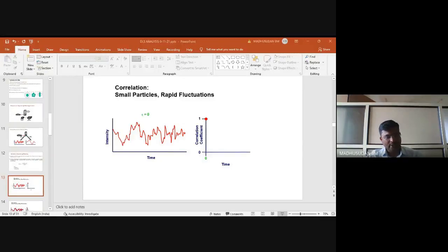So here, once after the 20 hours of ball milling had taken place, we took out the sample, and we know that smaller particle sizes are available, but they tend to be attracted to one another. I mean, the particles underwent the ball milling operation for a longer duration of 20 hours. There may be some high impact force. The particles, although they undergo a decrease in size, tend to agglomerate or cluster at this stage. So we are unable to distinguish or differentiate the smaller size particles at this stage.